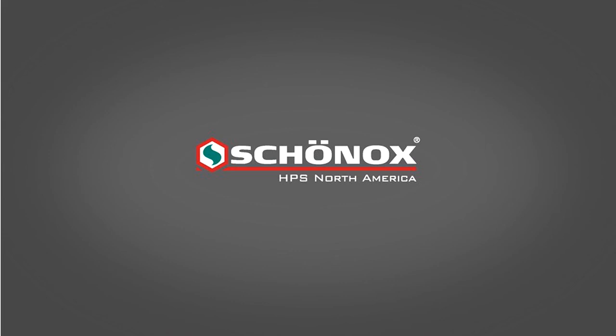Look at AP Rapid in itself. We have compressive strength of 3,800 in 1 day. After our 28-day cure time, we're at 5,800 PSI compressive strength and probably about 1,300 on the flexural strength for that product. In conjunction with AP Rapid Plus, compressive strength is 3,800 on day 1, around 6,300 PSI at 28 days, and we have a flexural strength of around 1,500 PSI. So very high strength gain, very high flexural strength.